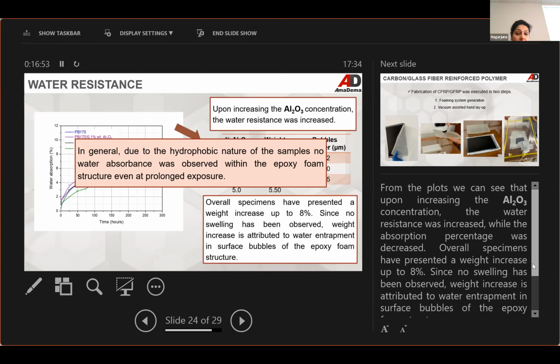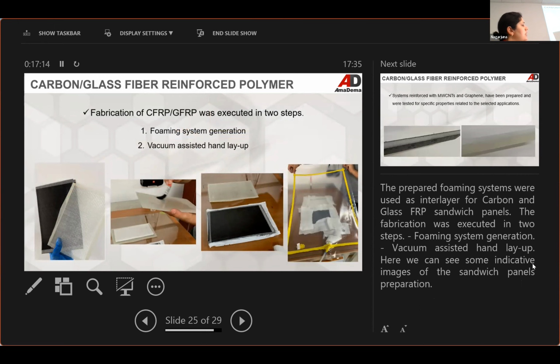Okay, as I told you in the beginning, the ultimate goal was to incorporate these foam structures as cores in carbon fiber reinforced polymers and glass fiber reinforced polymers. And this was realized in two steps. The first step was to synthesize this foam in a similar manner to how I have described earlier. So basically, you choose your reinforcement depending on the property you want to hit. You incorporate it in the structure, and then you cast the structure in a mold.